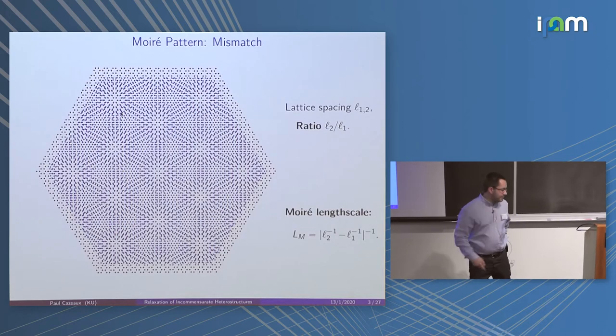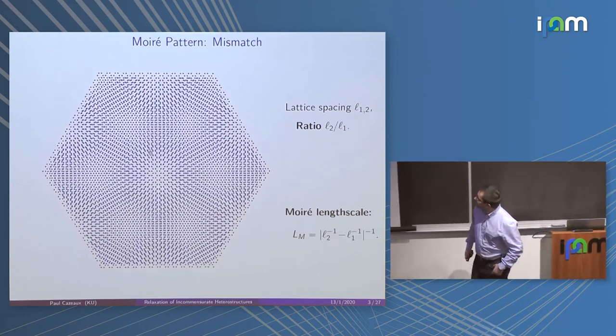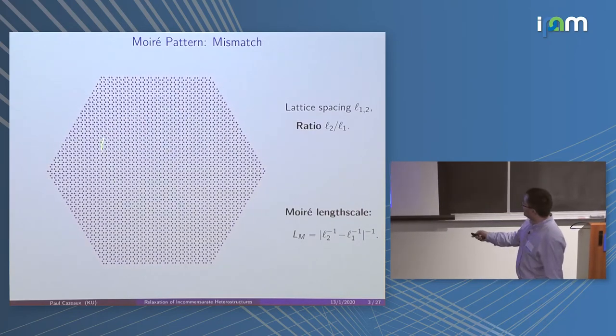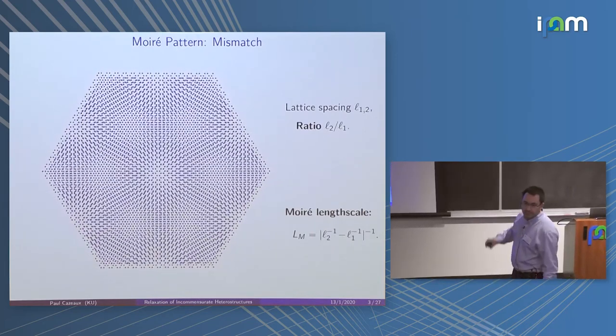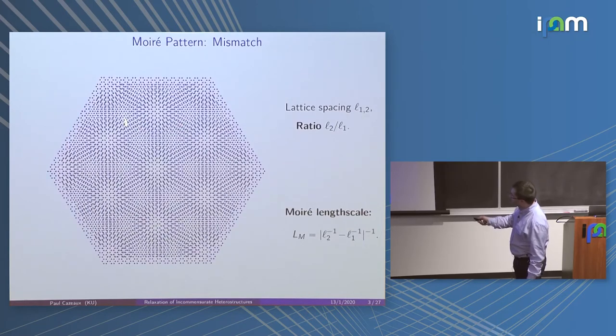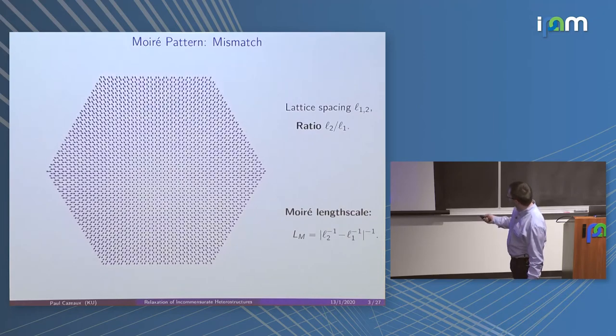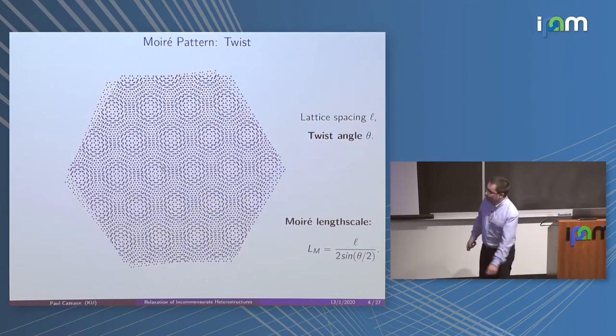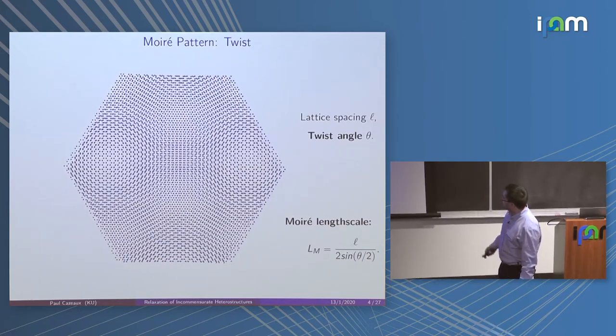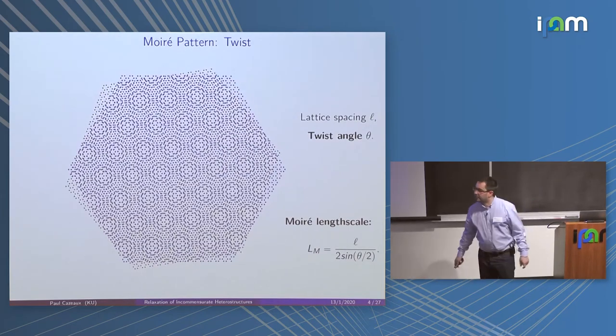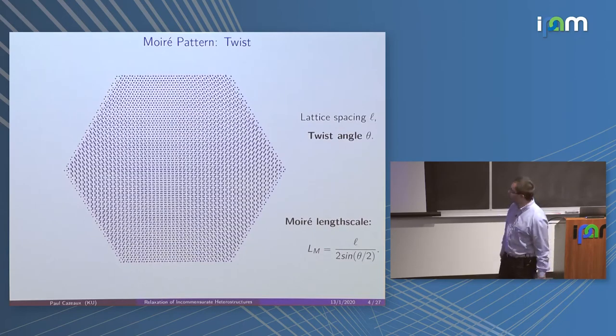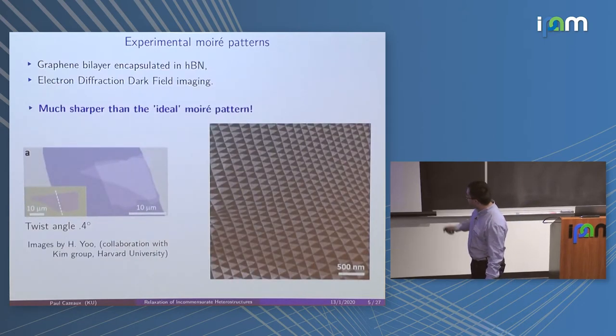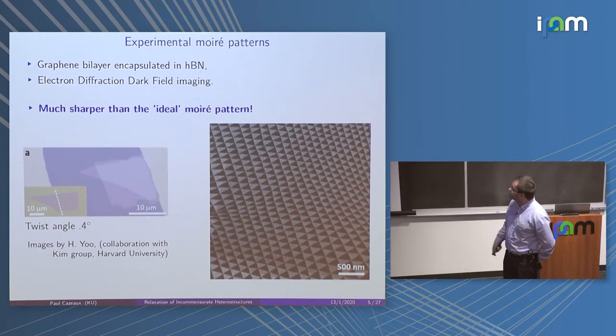In particular, we can see two kinds of moiré patterns. You have moiré patterns that appear like this due to a mismatch between the lattice constants — here there is no twist angle, just two hexagonal lattices superposed with a different lattice constant — and therefore a pattern appears when the ratio is not too close to one. Or I could also have a twist angle, which creates a moiré pattern that depends on the size of the twist angle: the smaller the angle, the bigger the moiré length scale. So we have these new length scales that appear in the system.